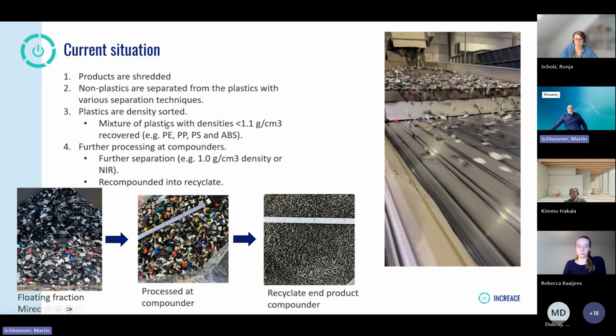This can be handled somehow by another density cut at 1.0, for example, or downstream NIR sorting to make more defined fraction out of it. And you see here, there's another size reduction in there. And in the end, you produce a regranulated material by re-extrusion and recompounding, meaning you add additives to make that material more suitable for industries in that second stage.